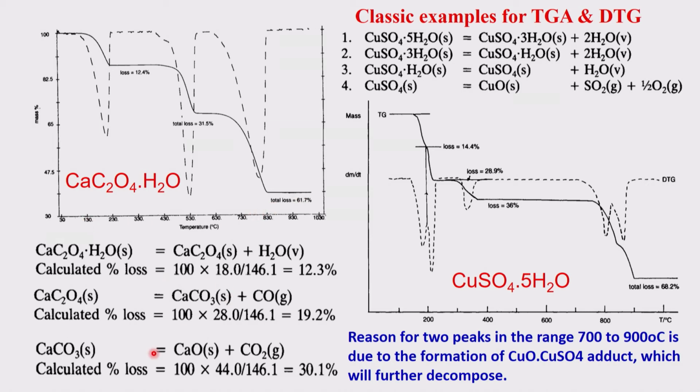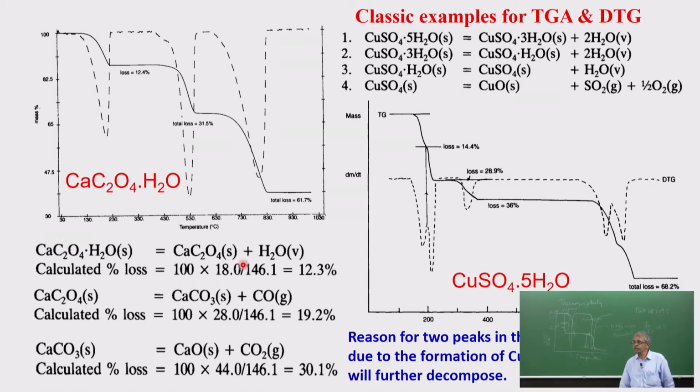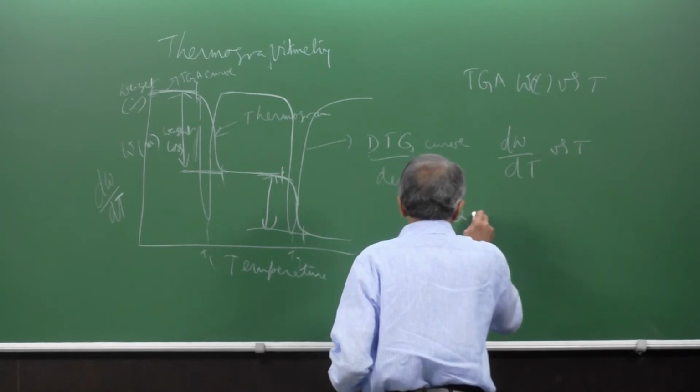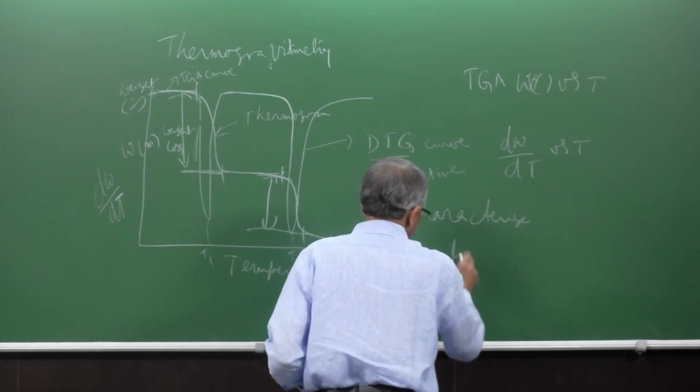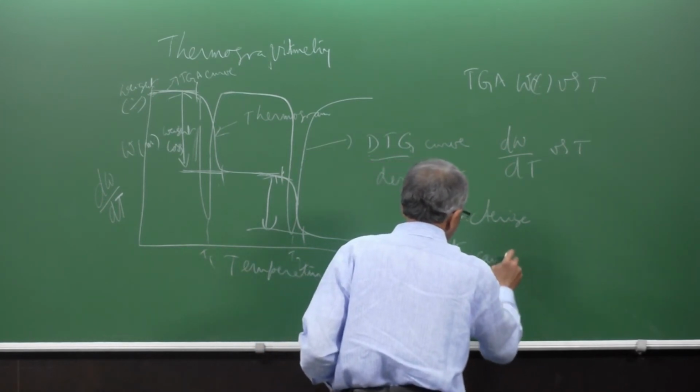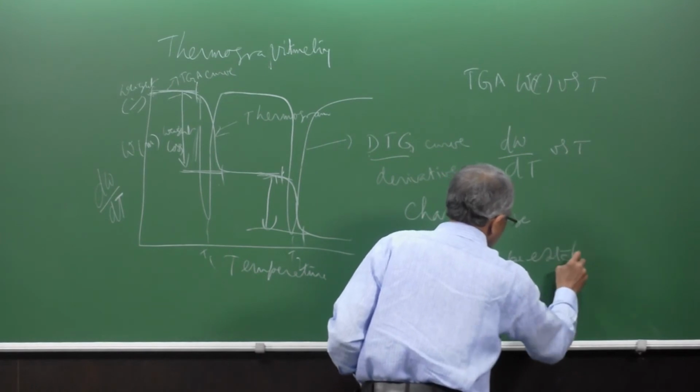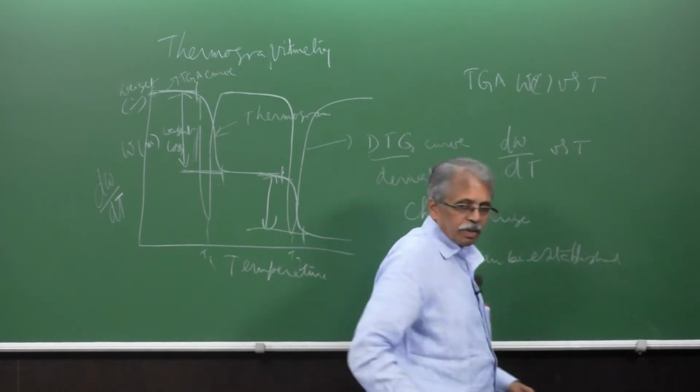So, now you got the process, the whole thing. Now, these temperatures are very characteristic. If they shift, that means there is some impurity, there is something else there. You can also find from the weight losses whether something else is added to this. So, you can analyze the compound characterization, and you can analyze the compound purity. So, you can characterize the compound as well as the purity can be established. So, all of these are possible here.